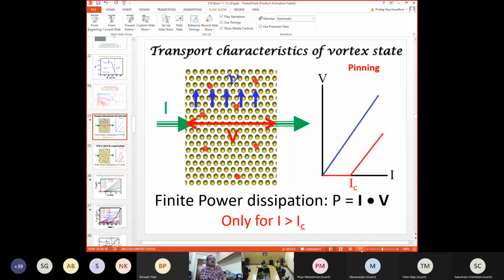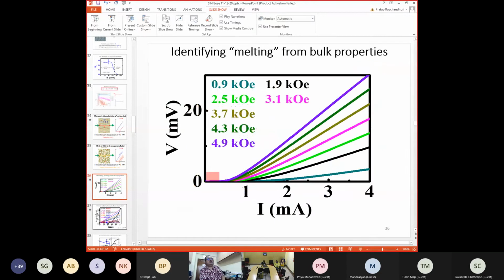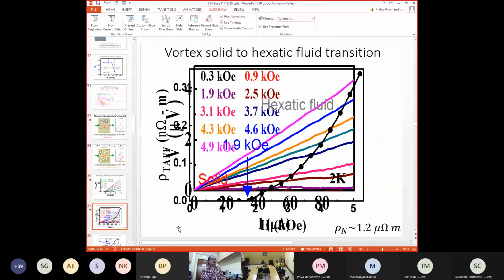So if I have to distinguish between a vortex solid and liquid, then I need to look at very small currents, which are much lower than the critical current. This is what I am showing here, and this is the IV characteristics. Now I have to look at this region here, which is at very small currents. Let me expand this region. And what you see is this.